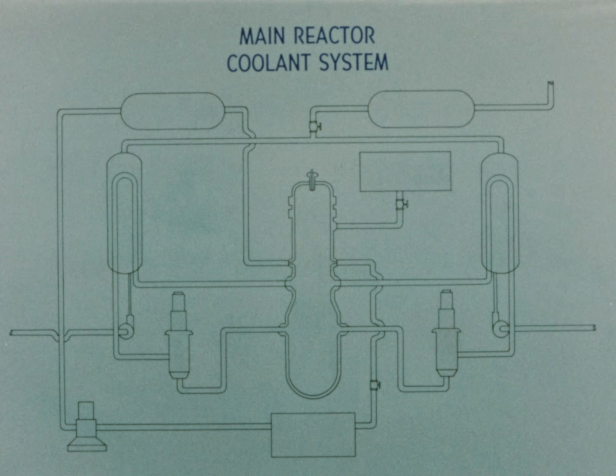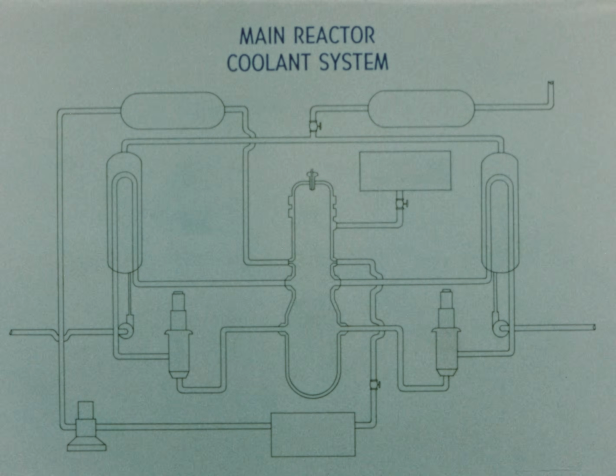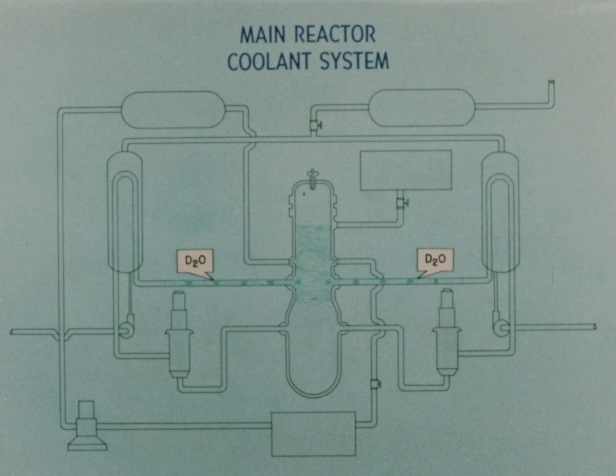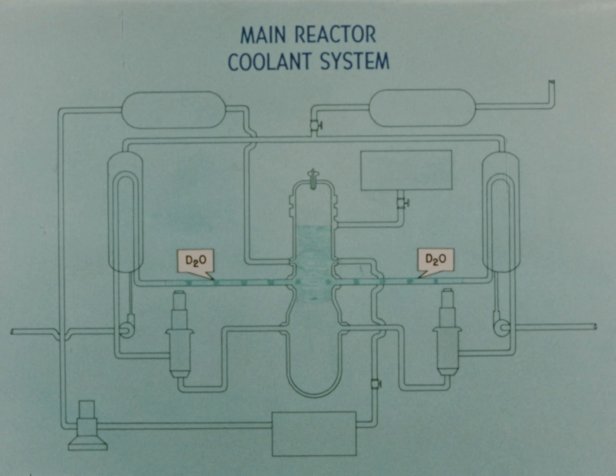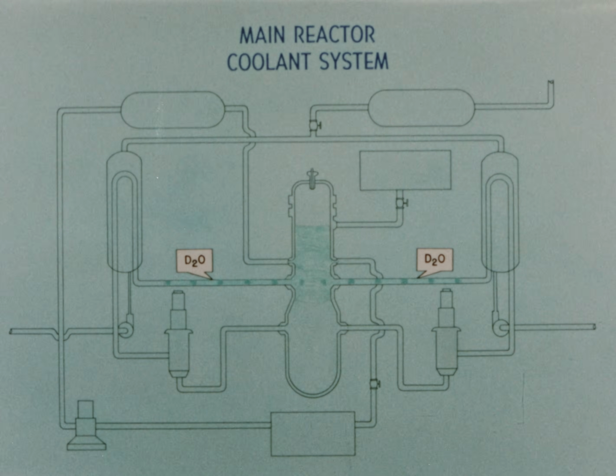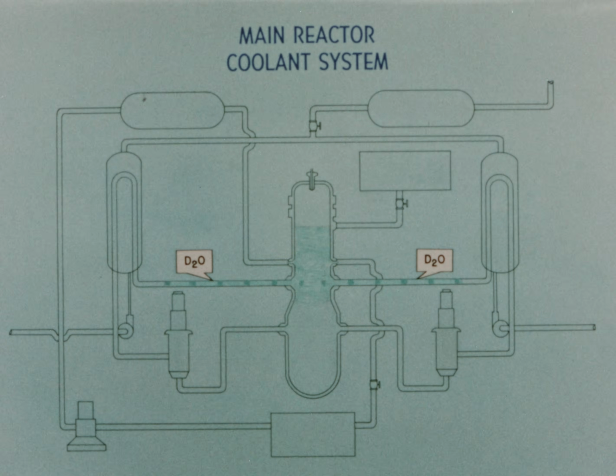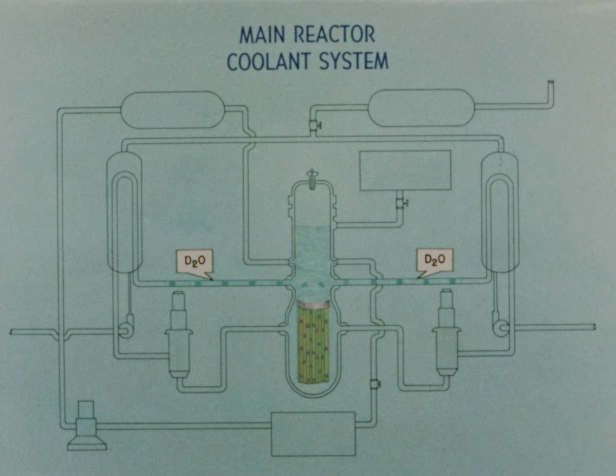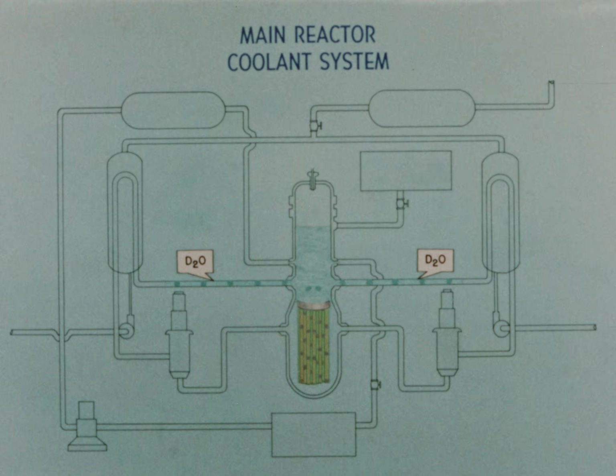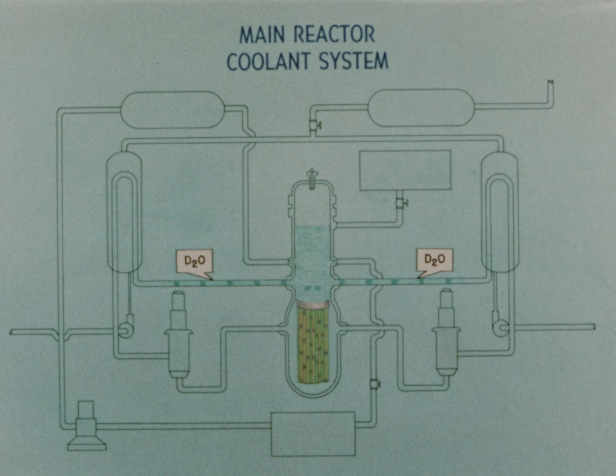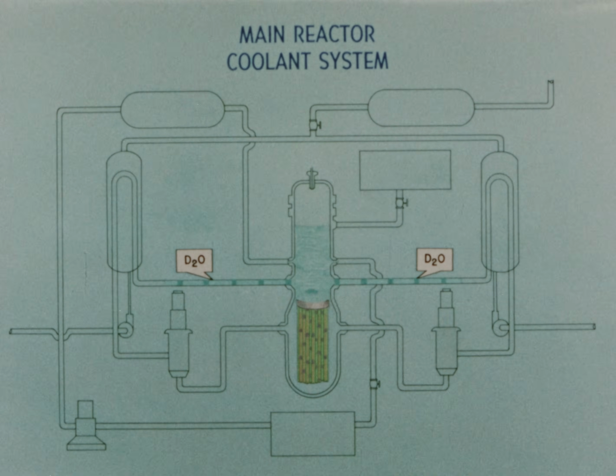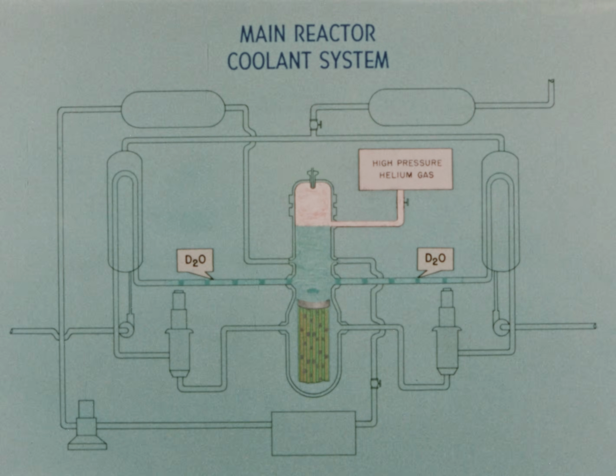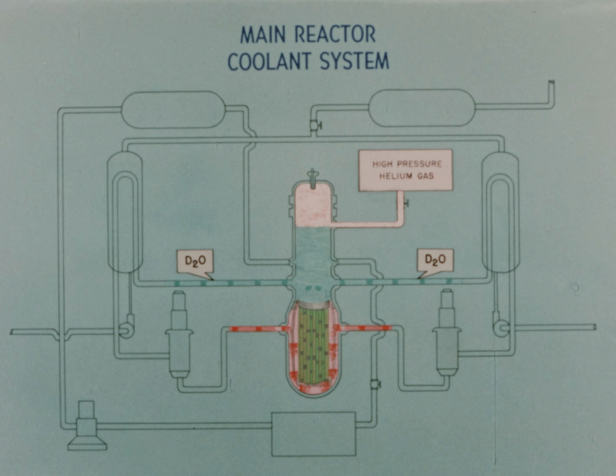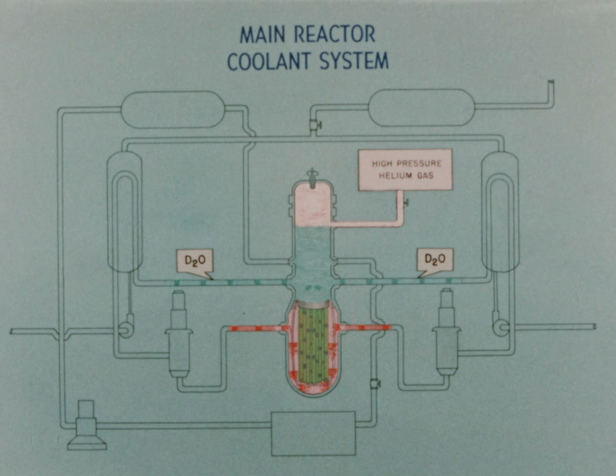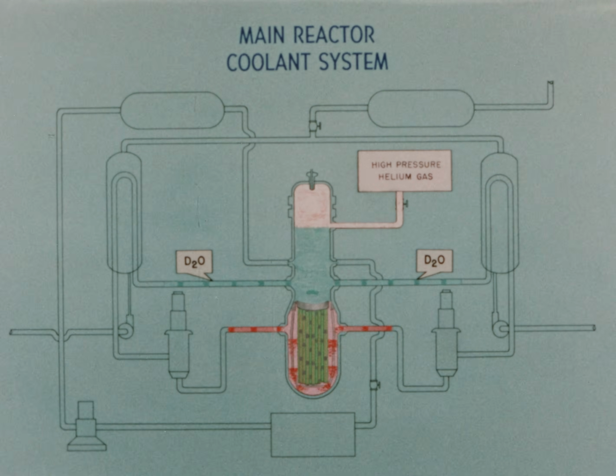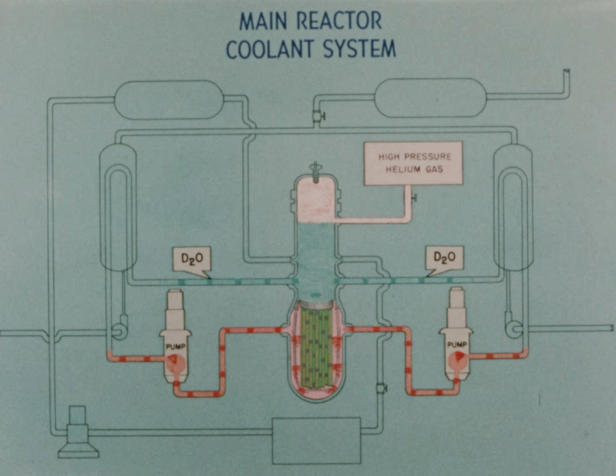D2O, at about 420 degrees Fahrenheit, enters the reactor vessel through two inlet nozzles. It then circulates downward in a forced flow through each fuel tube, cooling the fuel. The reactor system is pressurized with helium gas. Heavy water leaves the reactor at the core section and is circulated by two 4,800 GPM high-pressure pumps.